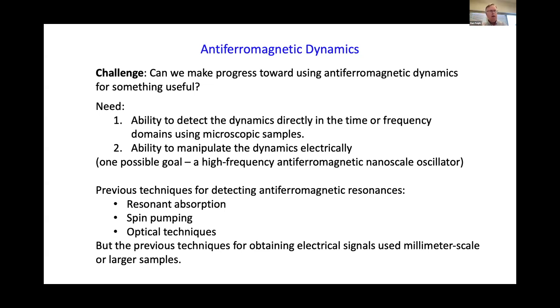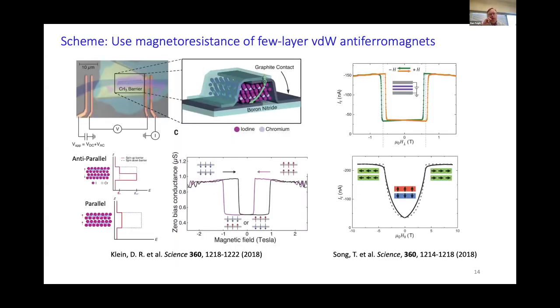So what's been done previously about direct detection of antiferromagnetic dynamics in the frequency or time domain are a variety of techniques, some electrical, like resonant absorption or spin pumping techniques, and some optical. But what's been done so far, at least in terms of electrical techniques, all involved macroscopic millimeter scale samples. And so one of the things we want to do is see if we could scale things down and get reasonable signals from much smaller samples. So the technique we had in mind was taking advantage of work by other groups on making tunnel junctions in which antiferromagnets were the barriers, the tunnel barriers. And there's been lots of nice work showing that in DC measurements, you can detect changes in the magnetic orientation between spin sublattices in van der Waals antiferromagnets by looking at their tunneling signal.